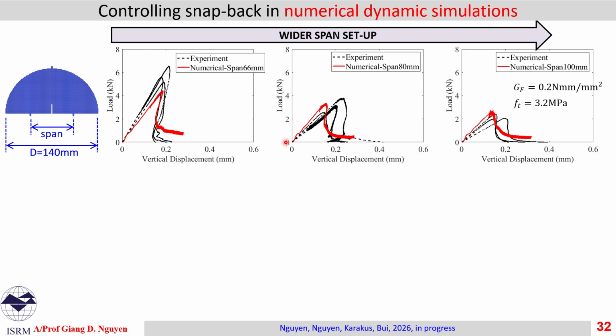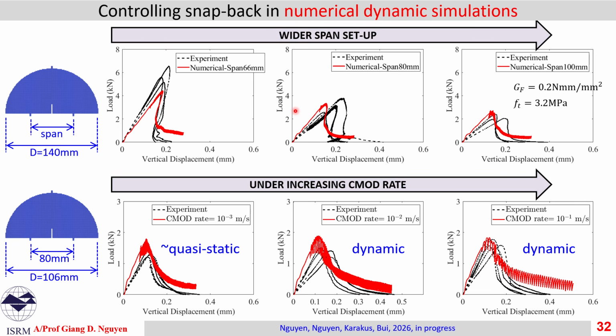This kind of control is used in our simulation across three different spans, 66 to 100, and as you can see here, we can capture snapback, or class 2 behavior, quite well. We can use a different type of specimen to explore the effects of dynamics on the behavior. Under this fixed configuration, we change the crack mouth opening displacement rate used to control the test, and we can still capture, at least to some extent, the behavior under different CMOD rates.